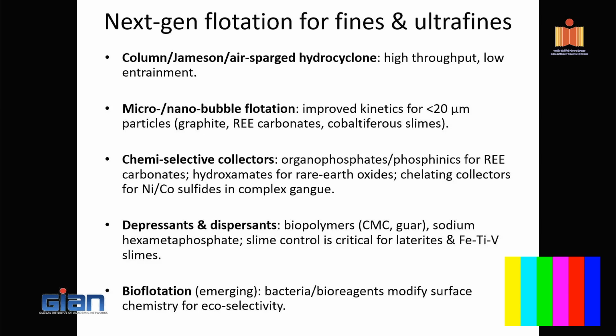The last one, bioflotation, which is emerging, where using bacteria or bioreagents, they can modify the surface chemistry for eco-selectivity. So this has been tested for chromite, iron-based separation and for bioleaching. But from a flotation point of view for critical minerals, it is still ongoing research. Particularly some of the European countries, Norway and Sweden, are trying to adopt bioflotation for some of these critical elements, including lithium and other components. But I think it is still at laboratory-range research, whereas other components have better maturity for immediate adoption for critical minerals.